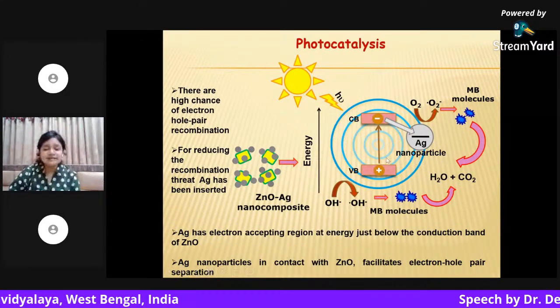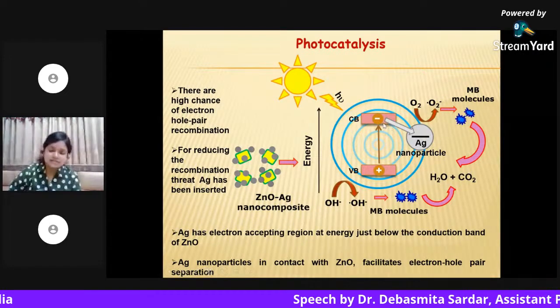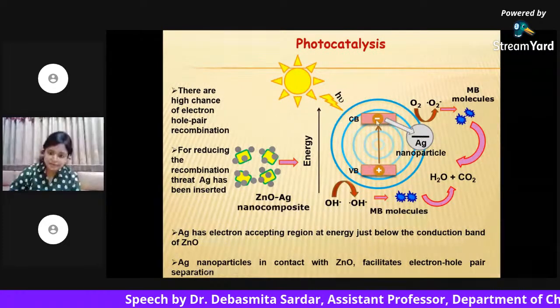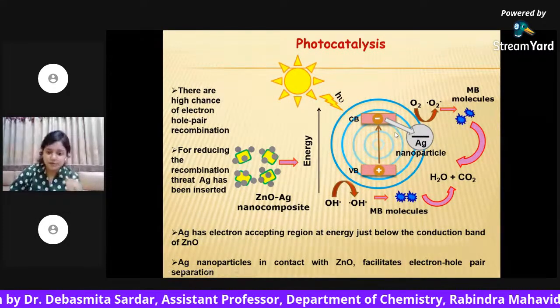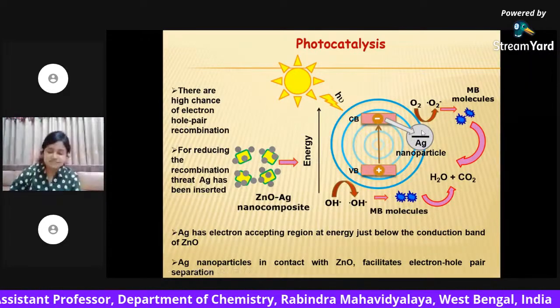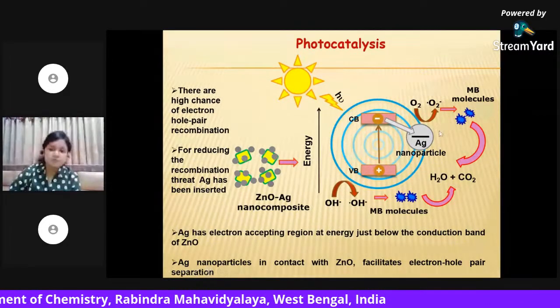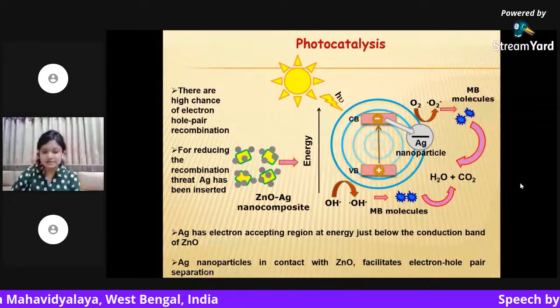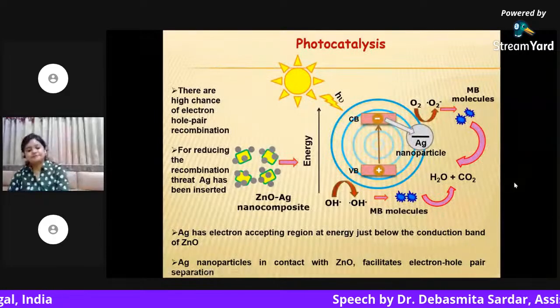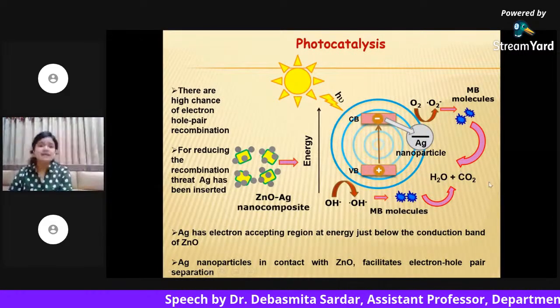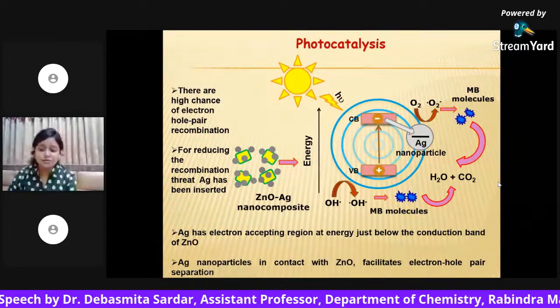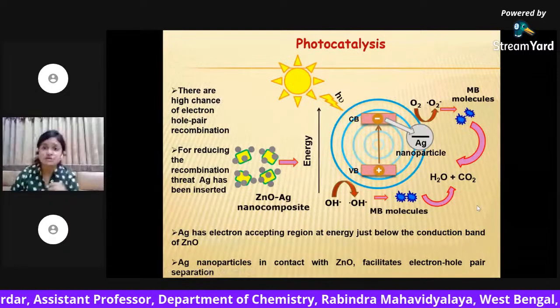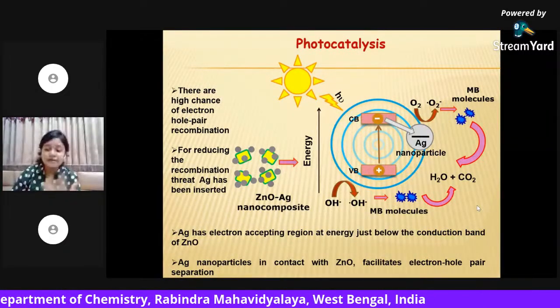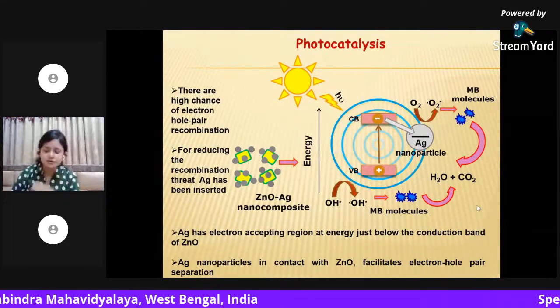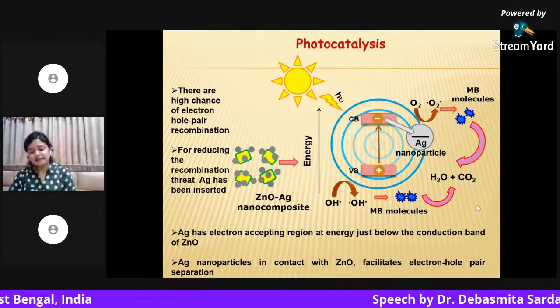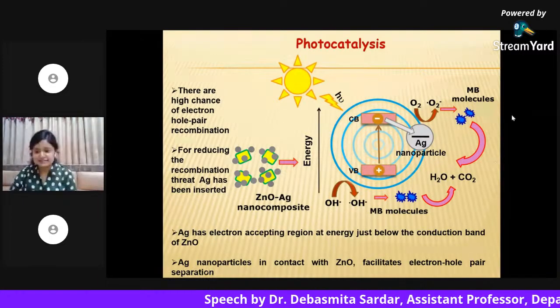So that's why we inserted silver nanoparticles just below the conduction band of the zinc oxide, so that they can trap the electron and recombination cannot happen. If the electron stays there, it can produce the superoxide ion, and the hole can produce the hydroxyl ion, and it can act as a photocatalyst. We can use that to clean our environment. Earlier I showed you how nanopaint has been used in the Mercedes Benz or in buildings in Dubai. Many buildings are coated with nanopaint because they are self-cleaning. They clean their own surface like that.